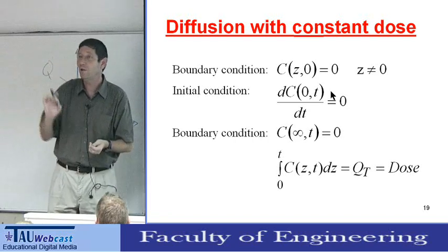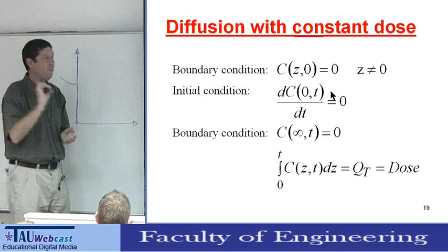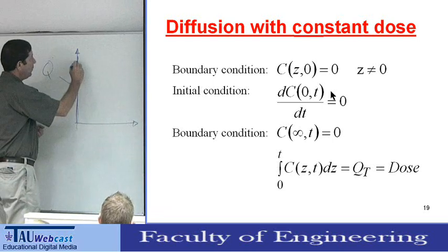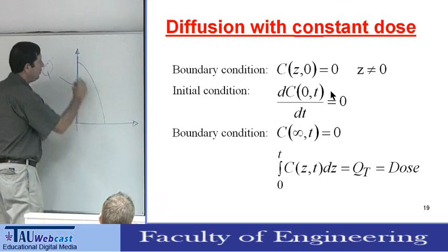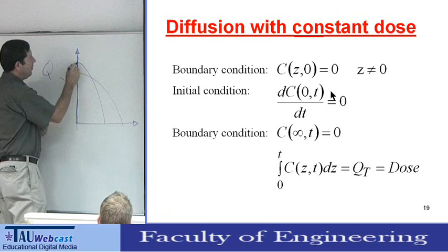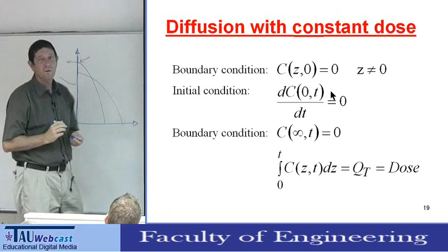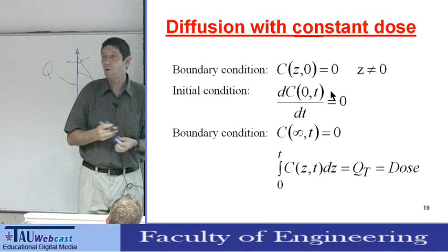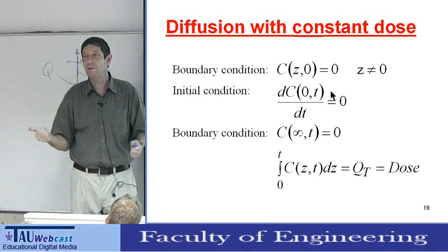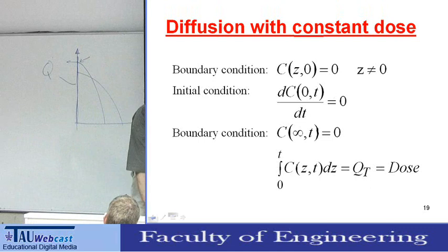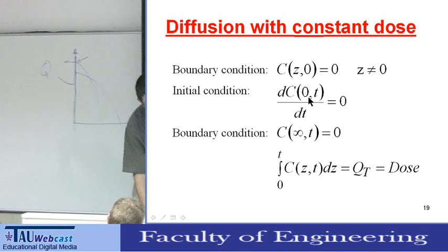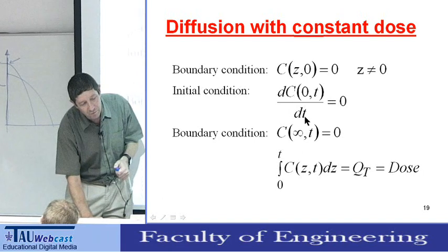It's a very definite number of atoms. And after a while, the atoms diffused inside. But we assume that next to the surface, nothing is going out because they all diffuse inside. And because there's no diffusion outside, the derivative equals 0.